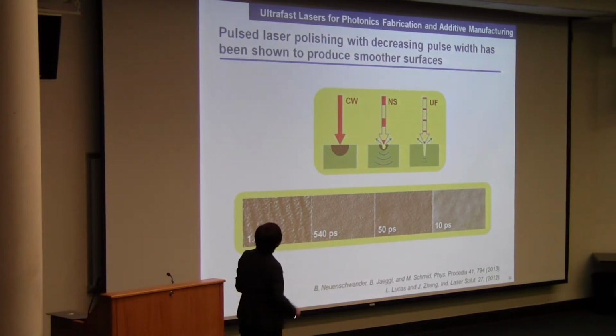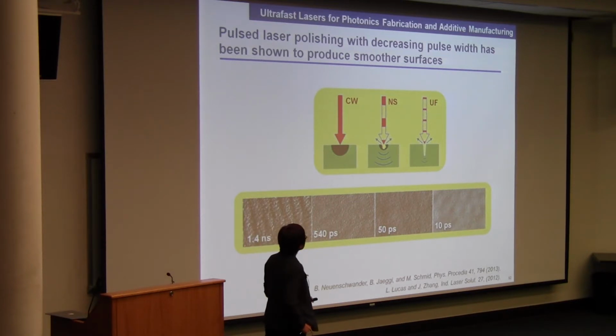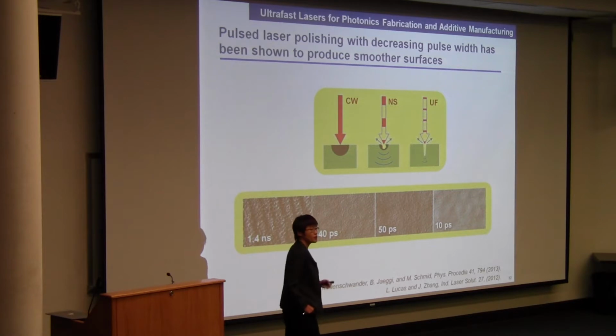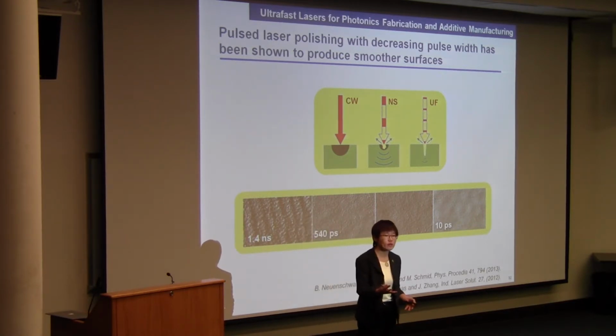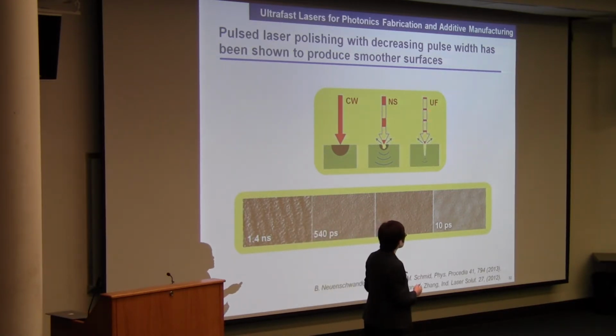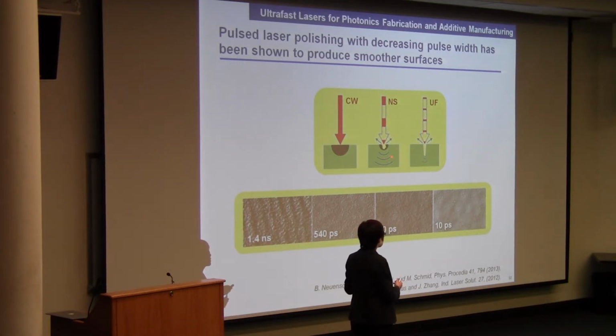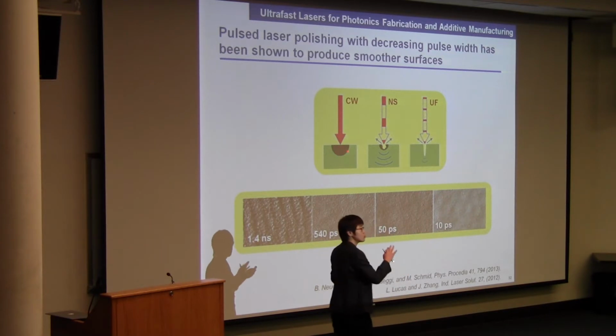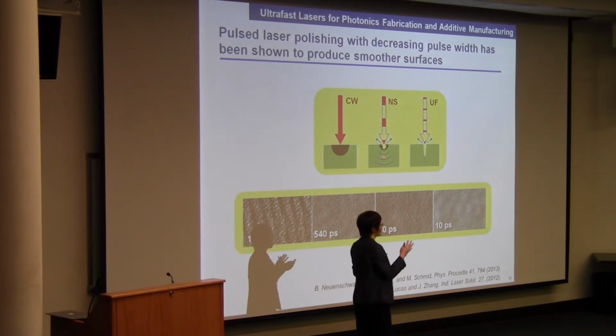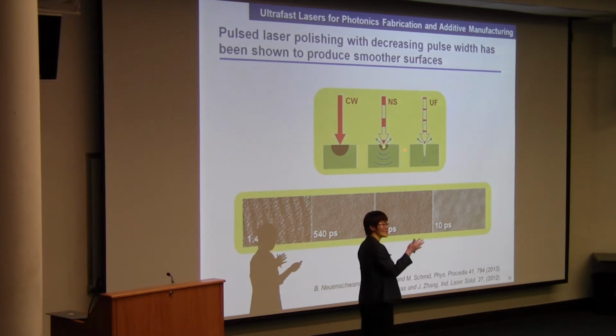Pulsed laser polishing with decreasing pulse width has been shown to produce smoother surfaces. There are different mechanisms. When you hear about laser, there's continuous wave laser, there's nanosecond laser, there's ultrafast laser. When they interact with the material, the mechanism is all different. For CW laser, you purely melt the material. You change the state of the material from solid to liquid, then resolidify it to a smooth material. For nanosecond laser, it's still through the heat effect. There's a heat wave, a shock wave. You interact with the material.